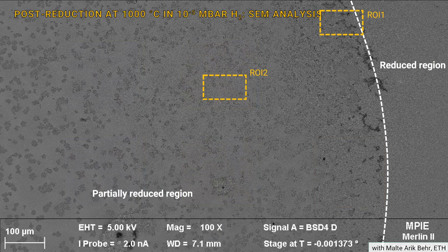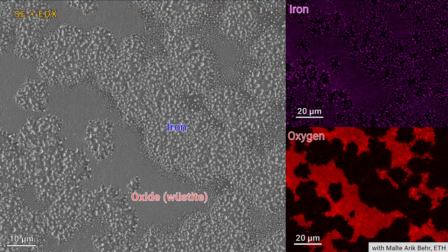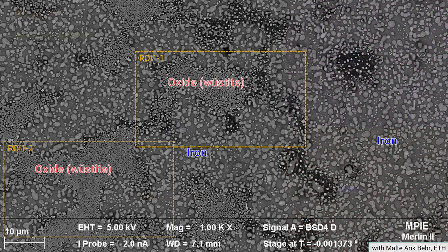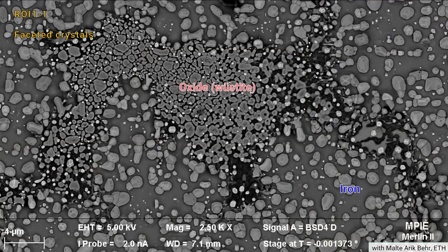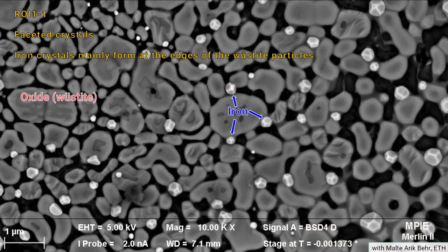Now the next step, this is again a collaboration with the colleagues at the ETH, here with Malte Arik Behr in Zurich, and we now try to study these things also in quasi two-dimensional wüstite films, which we again subject in situ to a hydrogen atmosphere, and then we study how the iron is really forming between the different wüstite layers. And that under reduced dimensions, in quasi two dimensions. Here you see how these very beautiful shapes of the iron nuclei are forming.